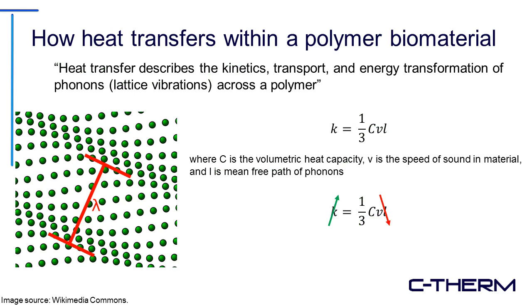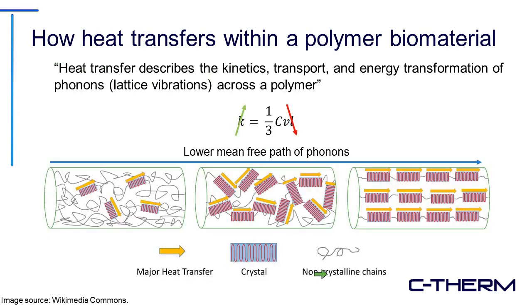There's a variety of different ways that we can actually affect this and increase thermal conductivity. And one of the ways that we could do this is by increasing crystallinity inside of the polymer material. So with very low crystallinity inside of a polymer material, we get very insulative-type properties, whereas if we increase and orient some of these crystalline domains inside the polymer, we get higher thermal conductivity.